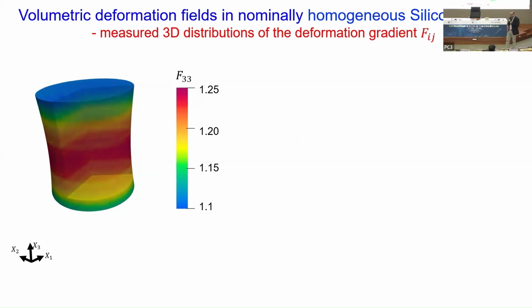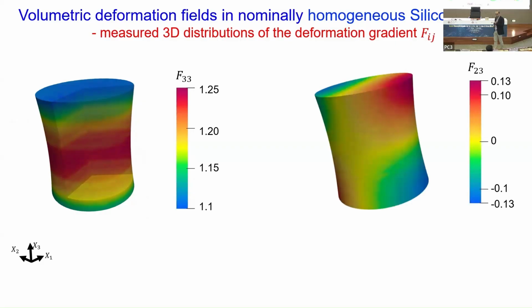And so what you're getting here is less strain near the platens, the top and the bottom, and more strain in the middle. That's not a surprise because of the gluing boundary conditions that were being used. If you look at a shear component of the deformation gradient, like a shear strain, you're seeing this anti-symmetric pattern, red, blue here like that. And that's because of the glued boundary condition, this specimen is waisting. And because of the waisting, you're getting that shear strain. So again, not a surprise. You've done all these very complex measurements and you don't think you've learned anything dramatically new.